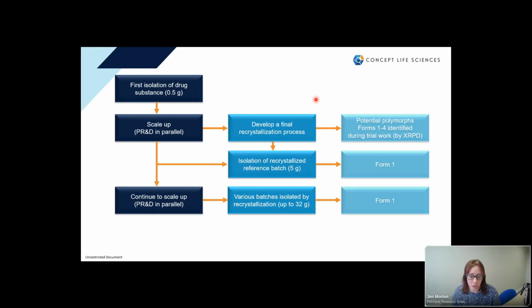We then selected one of our recrystallization conditions, and we moved on to use those conditions to prepare a reference batch. Now, those conditions involved an antisolvent recrystallization, where you dissolve the material in a solvent it's happy to be in, and then you add a solvent that it is less happy to be in, and then having changed the conditions, it will precipitate out. So we isolated our reference batch, and that came back by XRPD as form 1, which matched that particular trial.